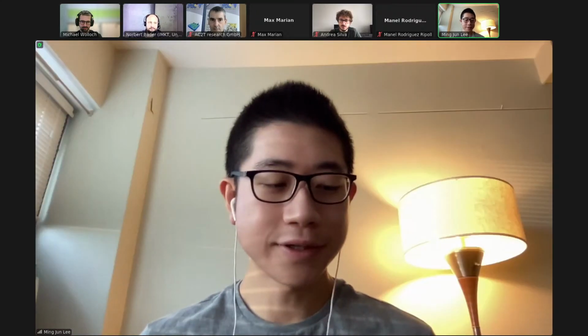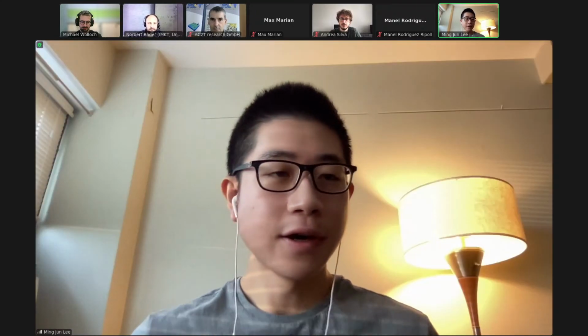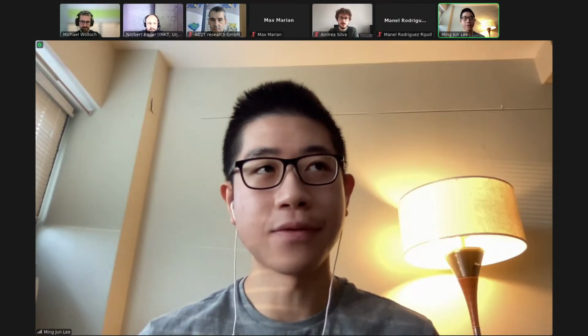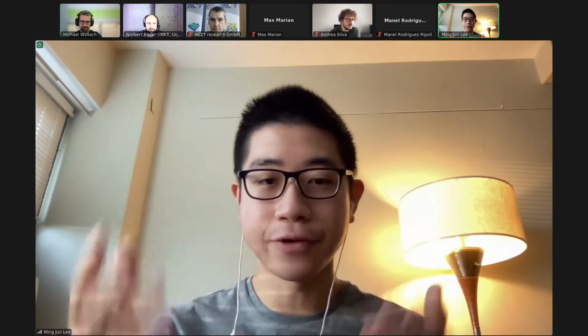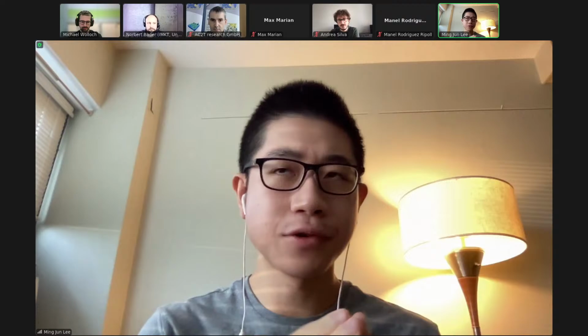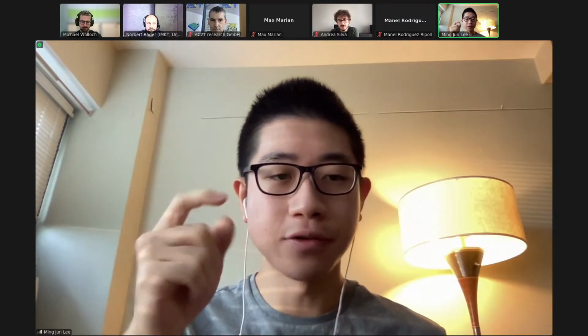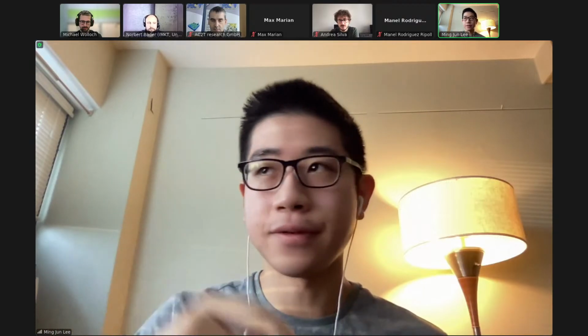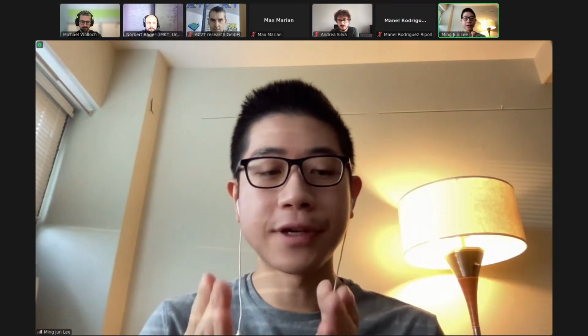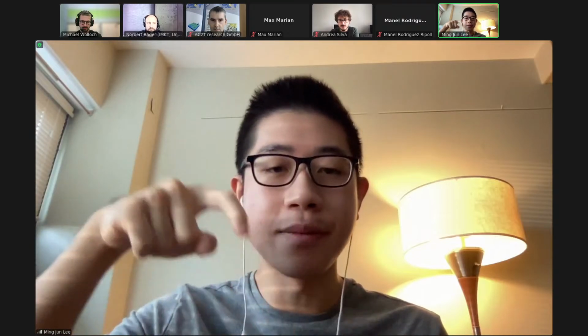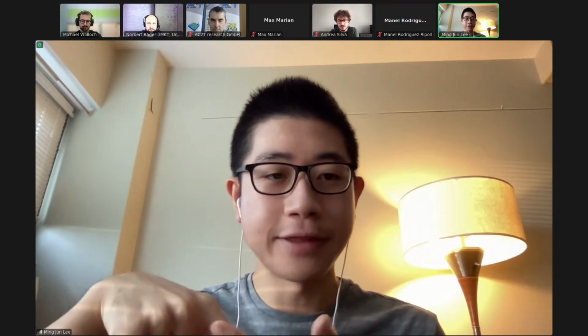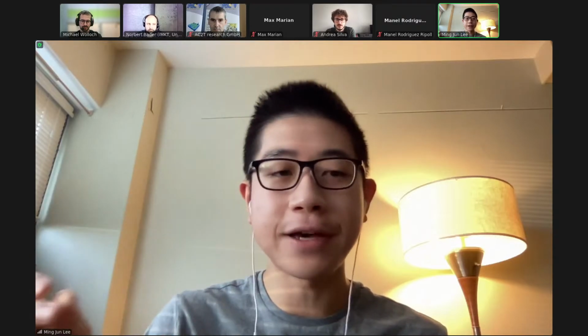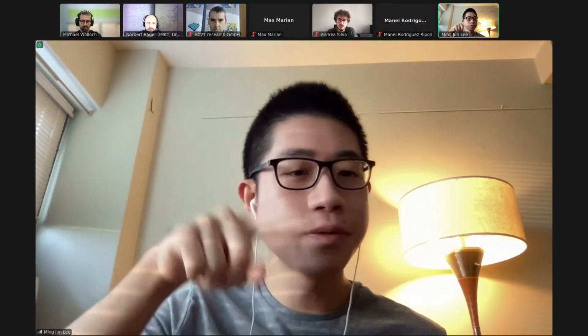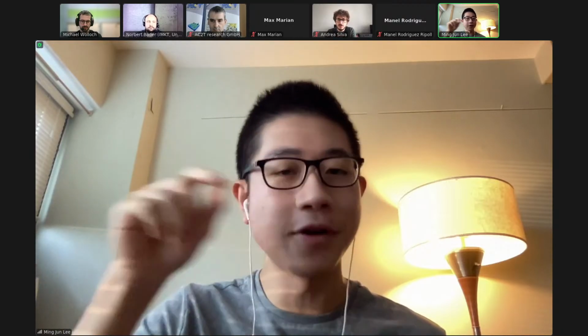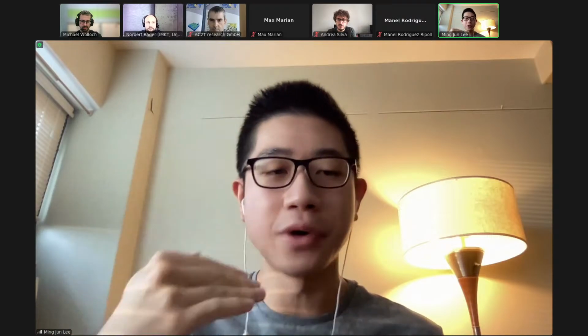Okay, so to answer the first question regarding scale effects, one particular problem that we have when we try to measure hydrogel friction with a tip is that if you use too small of a scale, so maybe a very, very sharp tip that we can purchase, you will actually puncture into the mesh of the polymer network. And then you get a lot of stick-slip effects, and the friction maps turn out to have a lot of overblown pixel values. You just see white spots everywhere. So that's the small extreme.